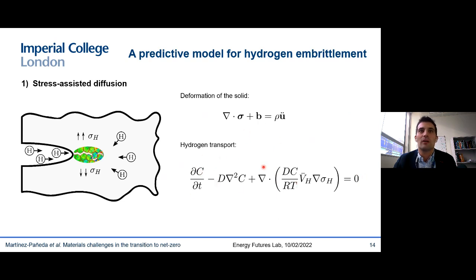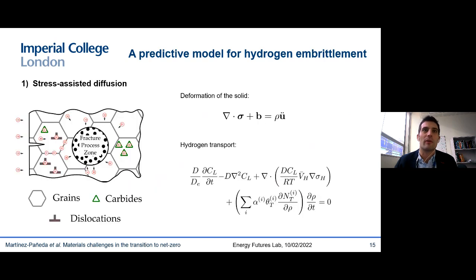So hydrogen will travel driven by gradients of concentration, but also, as you see here, by gradients of hydrostatic stress. Hydrogen accumulates in regions where the volumetric strains and the hydrostatic stress are larger, so there's more space due to lattice dilatation. And this is, by the way, the simplest model that you can use for modeling hydrogen transport. In reality, hydrogen not only travels through the lattice, but it's also trapped in some microstructural features, such as grain boundaries, carbides, dislocations, and so on. So we have also developed more sophisticated models that account for those things.